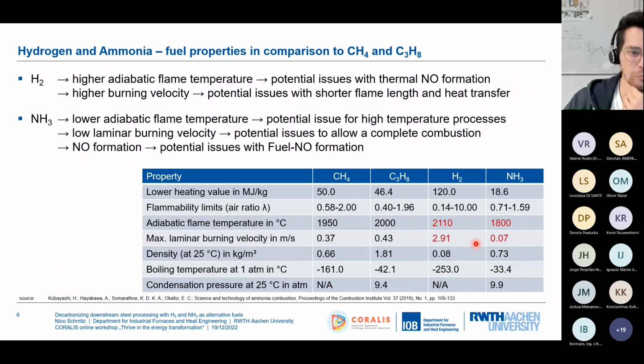If we now look at ammonia, it's quite the opposite. The adiabatic flame temperatures are lower, which could be an issue for high temperature processes because we need to generate high temperatures to have heat transfer to the product. The second point is the low laminar burning velocity here, so low reactivity. This could be a possible issue for complete combustion because the combustion kinetics are slower.